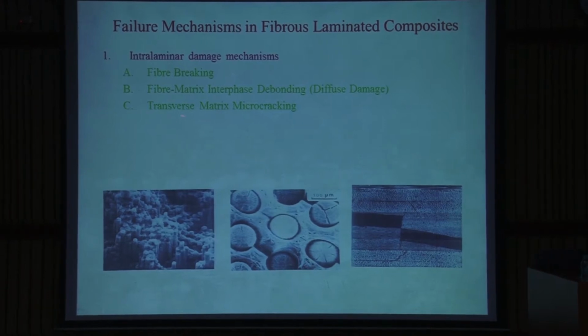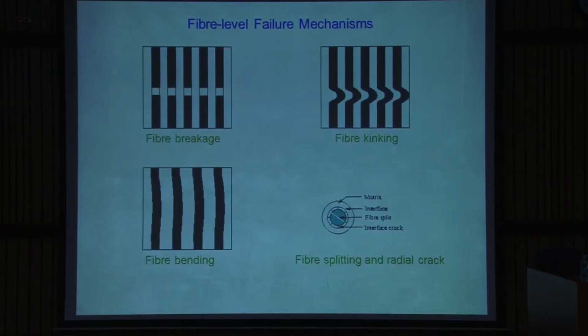Then another form of the damage or failure is the transverse matrix cracking. There is a crack in the ply. This is a laminate, so it has different plies together. What you see here is that in this ply, the fibers are going into this screen. You can see here that there is a crack which is going through the thickness of the ply. Similarly here there is a crack going through the thickness of the ply. Similarly here.